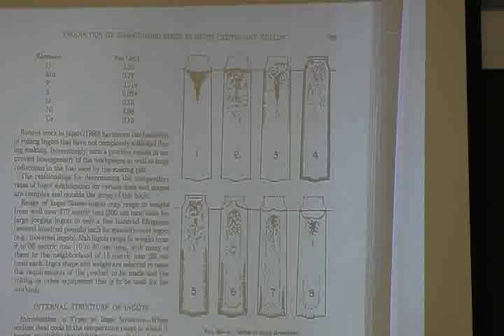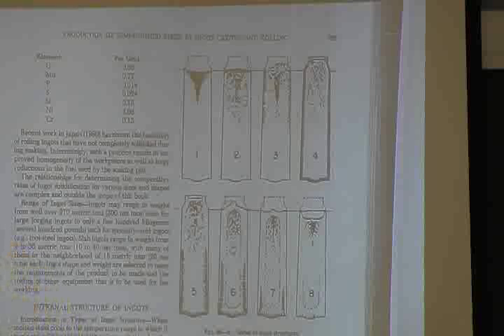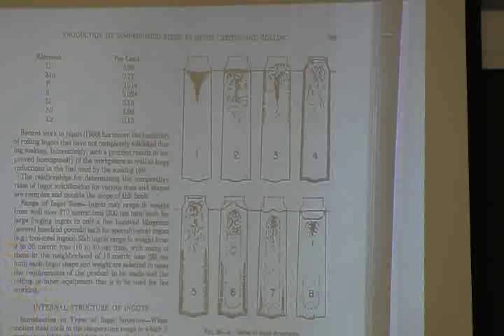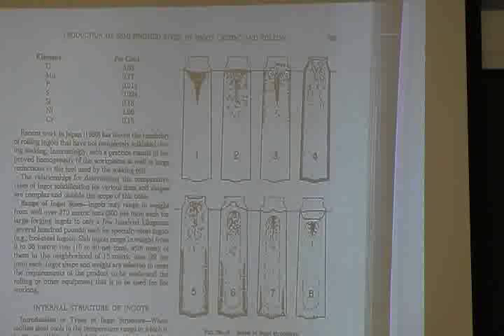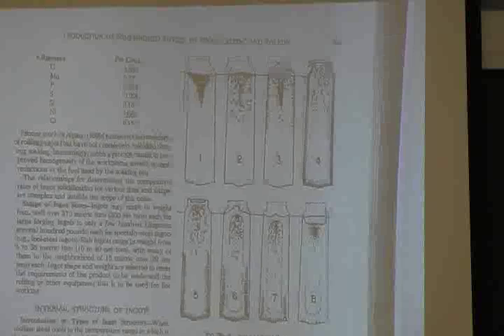If you have done something to get rid of the oxygen in there, like adding aluminum or silicon or manganese, you'll end up with no carbon monoxide boil, and you'll get solidification shrinkage. You're going to have to cut off the top third of that ingot. Okay? So to make really heavy plates above about 4 or 5 inches thick, we still have to use ingot technology. But today, 97% of the steel in the world is made by continuous casting.